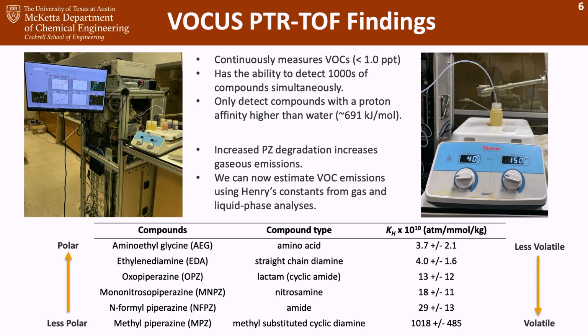So with the help of the Vocus PTR-TOF, we're then able to quantify our gas phase emissions and relate those to our liquid phase emissions and develop what's called a Henry's constant. This allows us to measure volatility of our species. So here are top species that we had found, some of our degradation products, and here are their Henry's constants. As they go down, they become more volatile. So in the future, we would be looking at mitigation methods that would most suit mitigation of some of these species down towards the bottom.